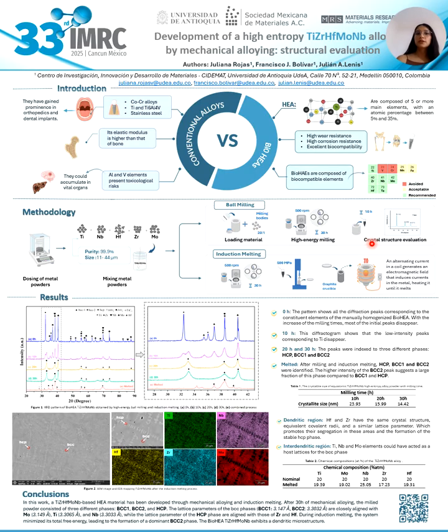It is important to mention that the idea is to evaluate how the different milling times could affect the crystal structure of the materials. For this reason, we took a small fraction of material every 10 hours and evaluated them through X-ray diffraction. For the induction melting process, the powder mixture was milled for 30 hours, then compacted to 500 megapascal using a hydraulic press, forming cylindrical pellets.